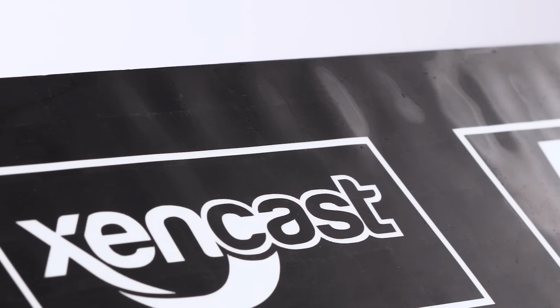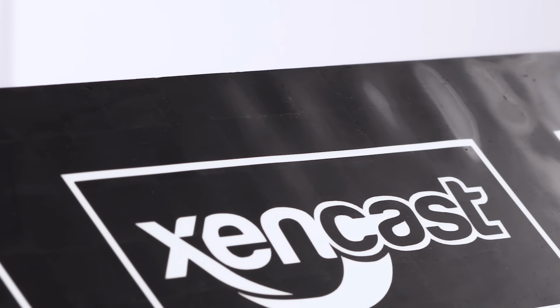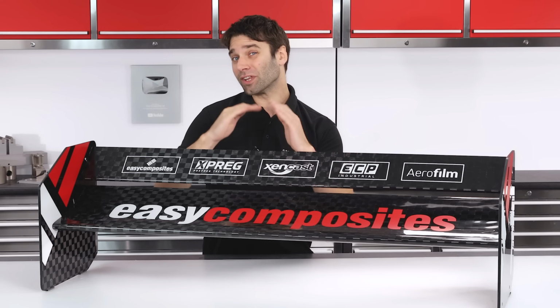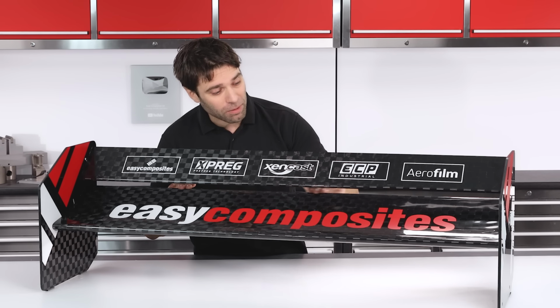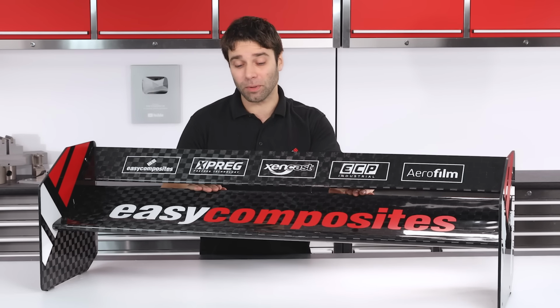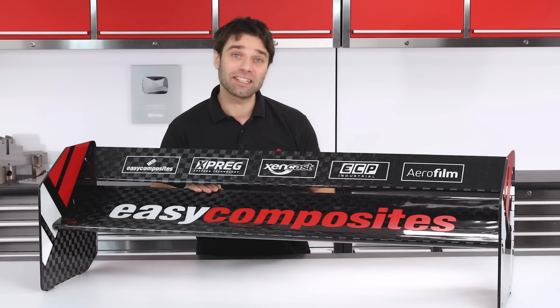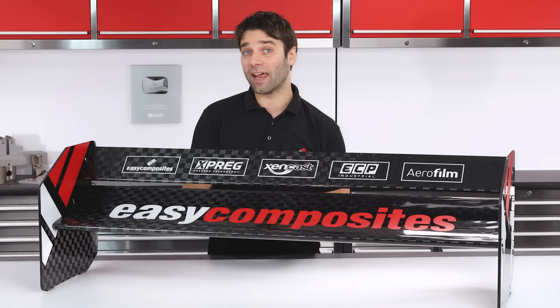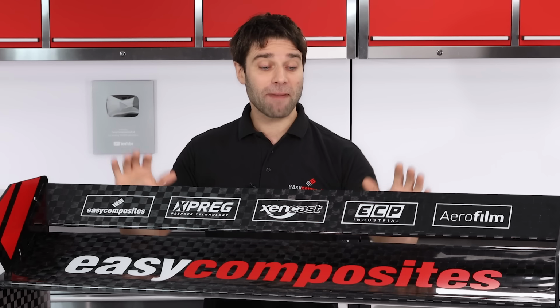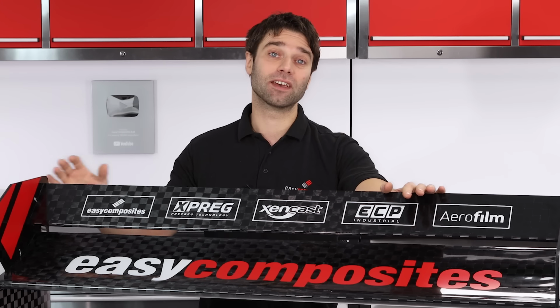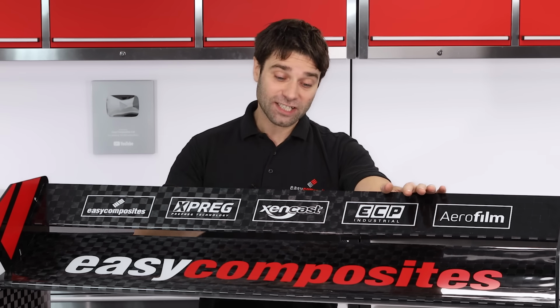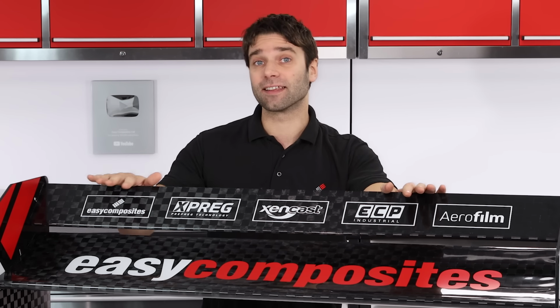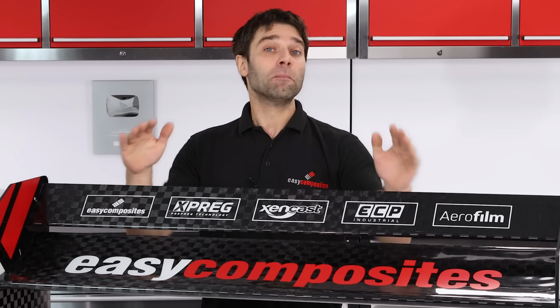The main one being the flatness of the surface that we're able to achieve. Without having a perfectly flat mould to laminate against, getting a small degree of ripple on these surfaces is almost unavoidable. Now, it is more noticeable on these concave faces, but honestly, it is only very slight and it's not likely to have any real bearing on the performance of the wing. A wing made like this is also going to be slightly heavier than its moulded counterpart would be. That's owing to the higher resin ratio that we're going to get in the laminate. But all in, I still think this is an excellent solution for producing high-performance one-off wings.